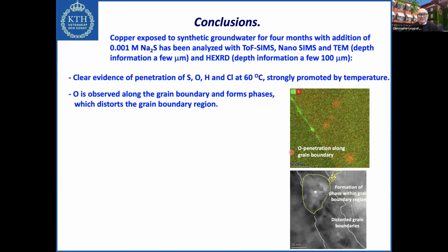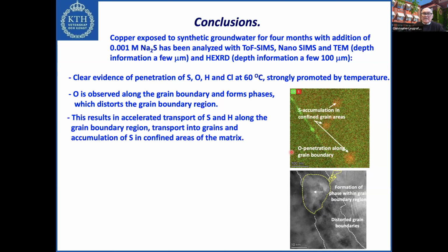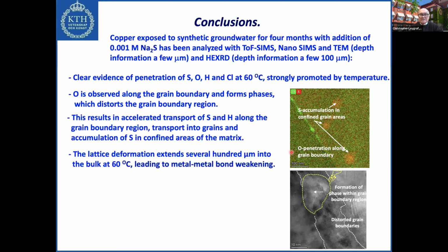And we see that oxygen is observed along the grain boundary and forms phases, which distorts the grain boundary region. And this results in an accelerated transport of sulfur and hydrogen along the grain boundary region and transport into the grains, and accumulation of sulfur in confined areas of the matrix. The lattice deformation extends several hundreds of micrometers into the bulk at 60 degrees, leading to metal-metal bond weakening. And interestingly also, we see certain holes or pits crossing the grain boundaries inside the material, which are enriched in sulfur, oxygen, hydrogen, and chlorine.